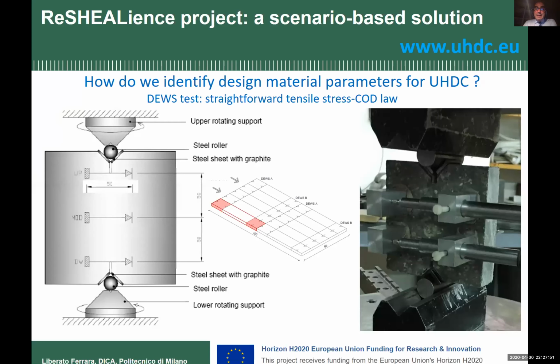And so we hypothesized, and we calibrated experimentally and numerically. We believed that this test gives us straightforward the tensile stress crack opening constitutive law of the material. Is this true?